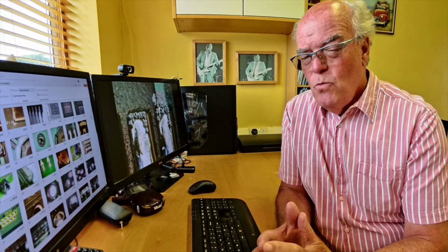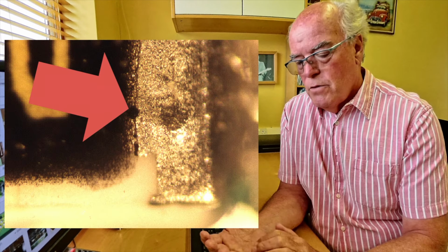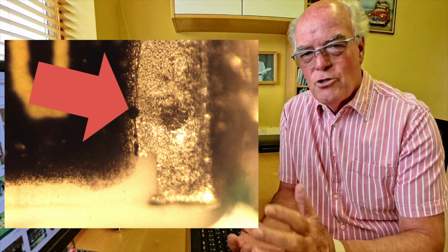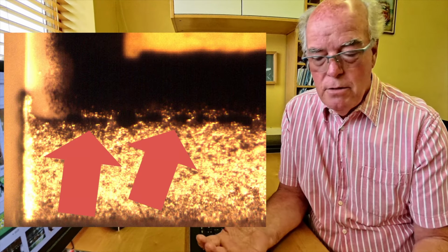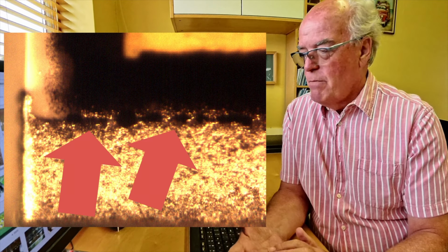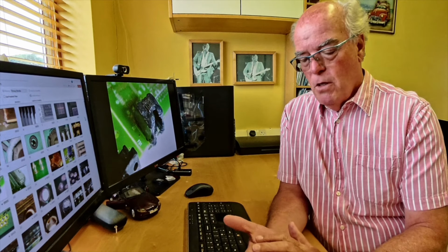Some of the areas that I've seen sulphur failures are on chip resistors, for instance. If you have material in your electronic assembly which is laden with sulphur for some reason, it may be packaging materials, it may be some sort of plastics, etc. If they're in a product which has a printed circuit board assembly in, it's possible for corrosion to occur on the surface of chip resistors.